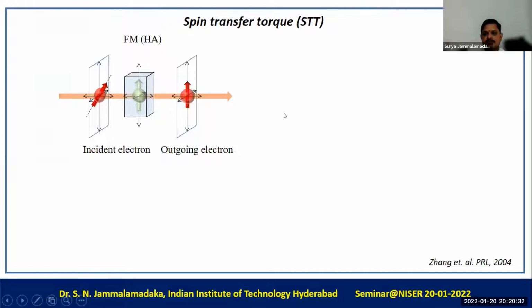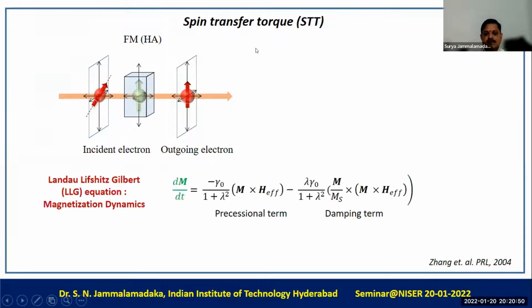So essentially, the domain walls in magnetic nanowires can be moved with the spin transfer torque phenomenon. This spin transfer torque phenomenon is very, very important to move the domain walls within ferromagnetic nanowires. Now the dynamics of the spin can be understood by the Landau-Lifshitz-Gilbert equation. Over here, the rate of change of magnetization consists of two parts. One is the precessional term, another one is the damping term.